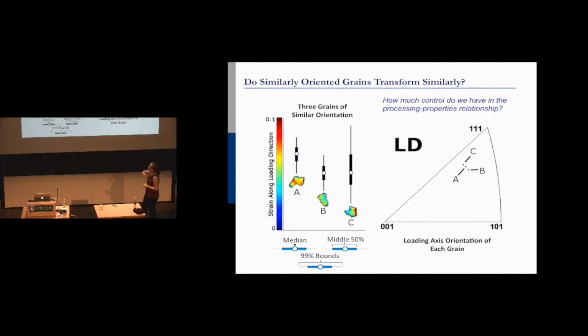You take three grains that are similarly oriented, and you look at basically strain as an extent of transformation. Here you have a lot of strain, right? Lots of transformation. And not a very wide range. So this thick black bar is 50%, and then the thin is like 99%. Each 5-micron grain has about 5,000 data points in it. Of those data points, 50% of them fall within this strain range, and 99% of them fall within this strain range. So we've got the equivalent of dropping like 5,000 data points inside of each grain. And so this grain is very high strain, and not a very wide range.